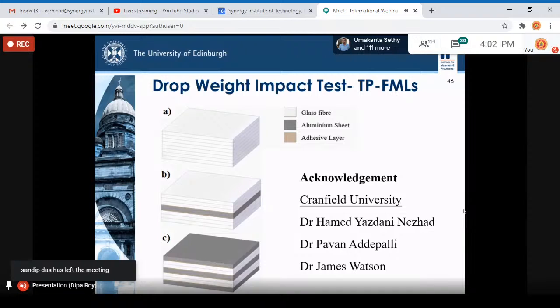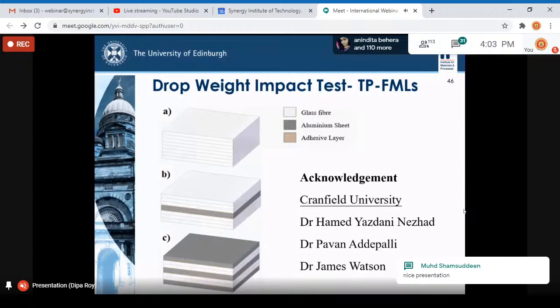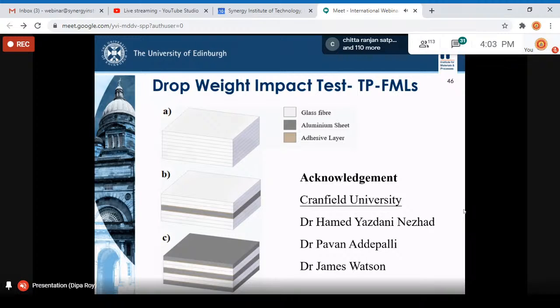Now, having optimized the bonding agent type, we then started to find out what our drop weight impact property would be, because for this kind of hybrid laminate, the key point is how good these laminates are at resisting high impact. The aluminum alloys, being highly ductile, can play a big role in absorbing these sudden high impacts. Composites don't have such good impact properties, especially acrylic, being a strain dependent matrix, which does not show any advantage in drop weight impact property. So it is important to find a way of enhancing the impact strength of the laminate, as that can work well in many sectors, including defense. This was the main objective for this work.